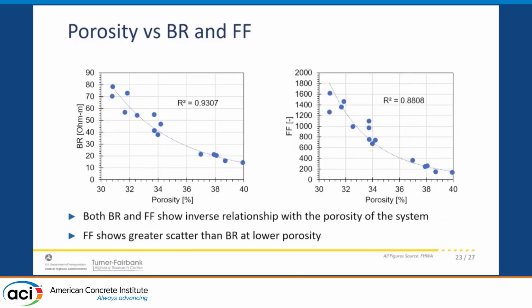And finally, this is the plot that I want you to remember. Basically, both bulk resistivity and formation factor show very good correlation with the porosity that we measure on the system. This was very important for us because it allows us to move forward with other tests.